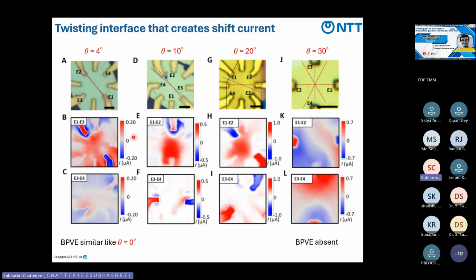So these people changed the angle, like 4 degrees to 30 degrees, and confirmed that by changing this stacking angle, the photocurrent gets diminished. When the angle is around 30 degrees, the photocurrent, almost like the BPV, the nonlinear photocurrent, was almost absent. So this is a technique we can follow, and we can do it with other materials or the same material, not only WSe2 or BP.